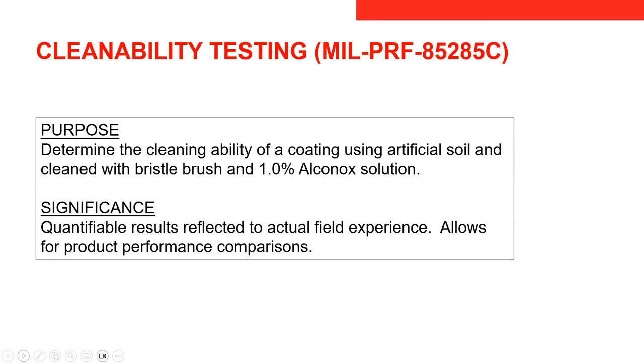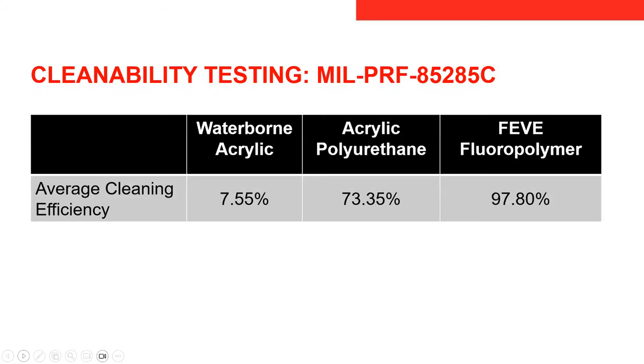So in this case, again, those three coatings that we just looked at with graffiti, after the cleaning with this artificial soil, the waterborne acrylic, only about 7.5% of that remains clean. So the majority of that was still stained. The acrylic polyurethane was much better at 73.35% that was able to be cleaned. And then the fluoropolymer was upwards of 98%. So almost completely removed that artificial soil.